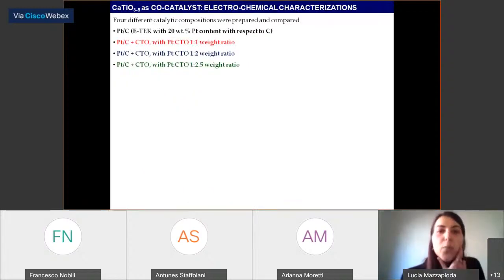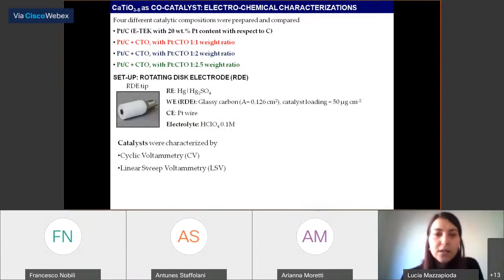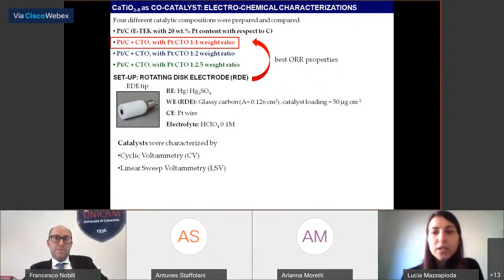Four different catalytic compositions were compared by using the RDE technique, whose setup is shown here. From this preliminary electrochemical characterization, the platinum-carbon plus perovskite sample, with platinum-carbon to perovskite in a weight ratio of 1:1, has shown the best performance in terms of oxygen reduction reaction activity. For this reason, it was used at the cathode side of the direct methanol fuel cell, whose performances were carried out